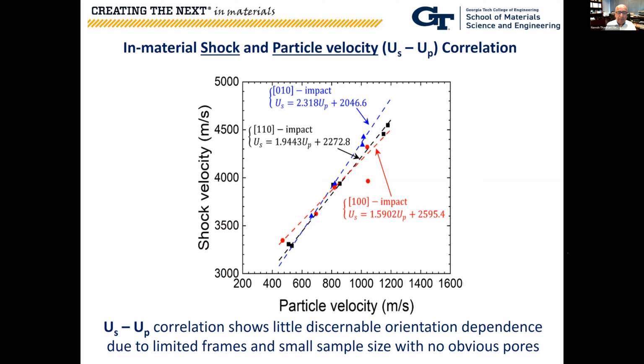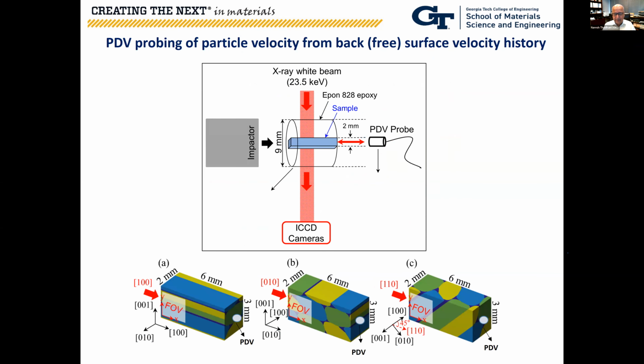So what else can we do? Remember, we also performed PDV analysis. The PDV analysis is performed on the back of the 6 millimeter long sample, while the X-ray probing is done in the front 2 millimeters, so we are not monitoring the same location. Plus the PDV is capturing a volume average response of the overall material, so you'd expect to see some difference. But the PDV was done at least to make sure that the shock and particle velocity correlation we obtain from X-ray phase contrast imaging is still within reasonable limits.